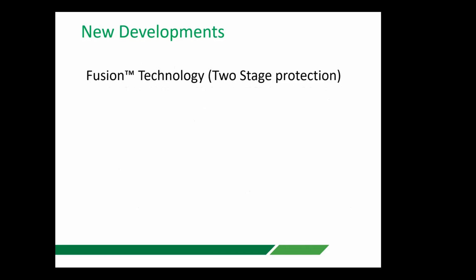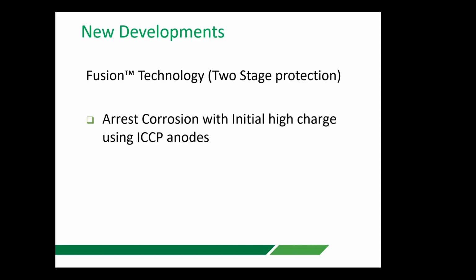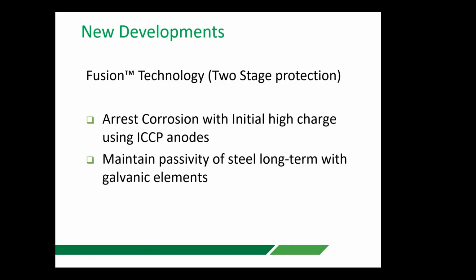Okay, so going on to new developments, and this is what we now call the fusion technology. It's a two-stage protection. Now, the one stage is obviously the galvanic protection that we've now almost perfected and we understand very well. But we wanted to have an impressed current element at the beginning. And the main reason for that was to try and stop corrosion. So if we are able to arrest corrosion with an initial high charge using the ICCP anodes, we can then maintain that passivity of the steel just by using a lower current density, which I mentioned at the beginning, called cathodic prevention. So an order of magnitude lower current density, and that can easily be achieved by the galvanic anodes. Just as I said, maintain the passivity of the steel long-term by using galvanic anodes.